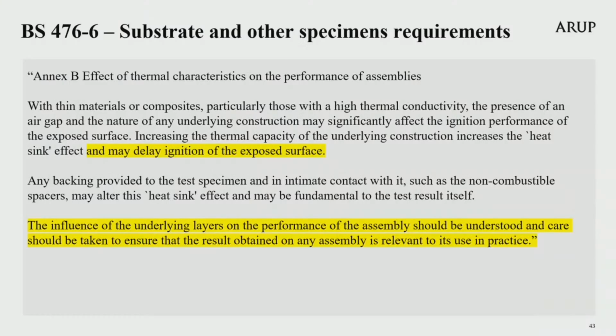Part 6 also makes a clear statement on the influence of underlying layers on the performance of the assembly when being tested in this combustion chamber. It advises that increasing the thermal capacity of the underlying construction increases the heat sink effect, and this may delay ignition of the exposed surface. It states that care should be taken to ensure the result obtained on any assembly is relevant to its use in practice.